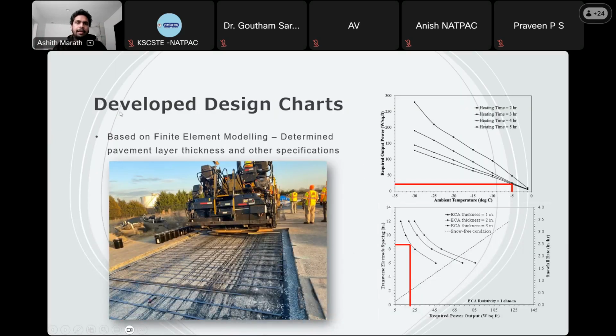With that, once we determined the electrical conductivity of the asphalt mixture, we moved on to the design phase of the full scale pavement. I used finite element modeling, which is only on the thermal side of the modeling, not the mechanical analysis. I developed a thermal model for the de-icing pavement, which can predict the pavement temperature under different ambient conditions. In this image from the test section constructed at Rowan University, you can see the steel bars placed in the transverse direction. These steel bars are a main component of electrically conductive pavements, which provide the electrical potential difference to the conductive layer.